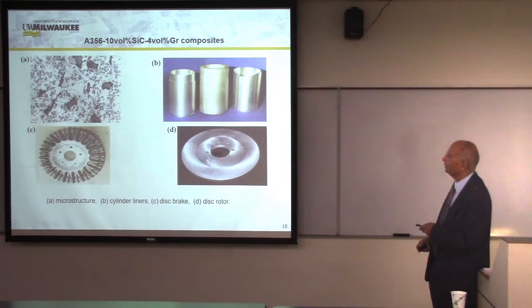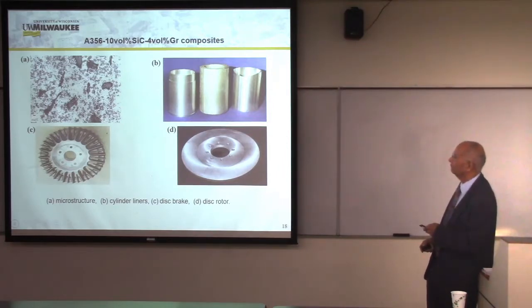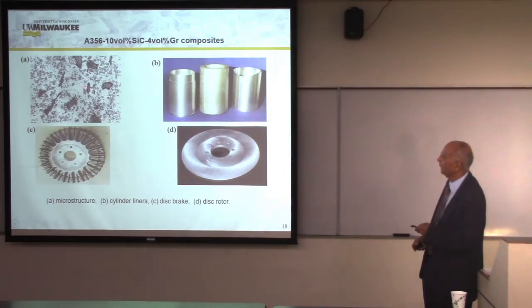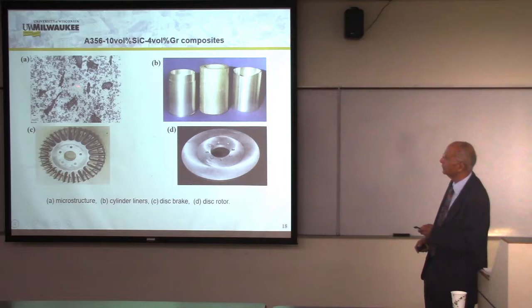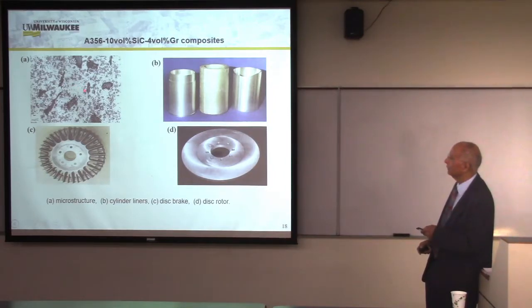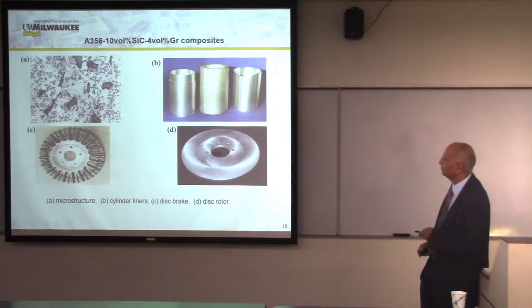Another set of cast composites that can be made in foundries were developed in our lab, where we have put silicon carbide and graphite, two different kinds of reinforcements, in the same liquid metal matrix. And this has an advantage because it prevents the flotation of graphite and settling of silicon carbide, and it combines high stiffness due to silicon carbide and solid lubricating ability because of the graphite.